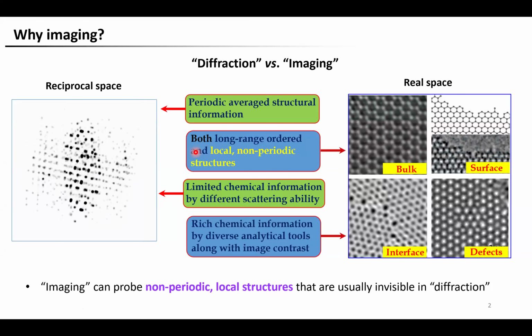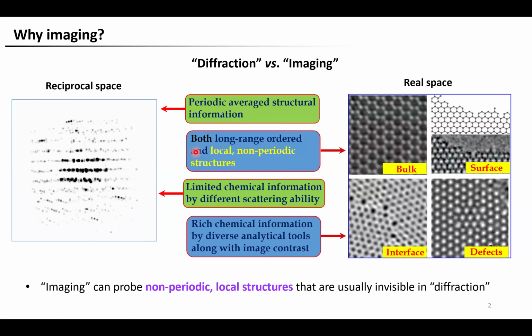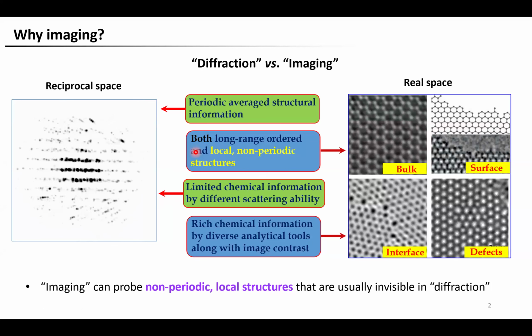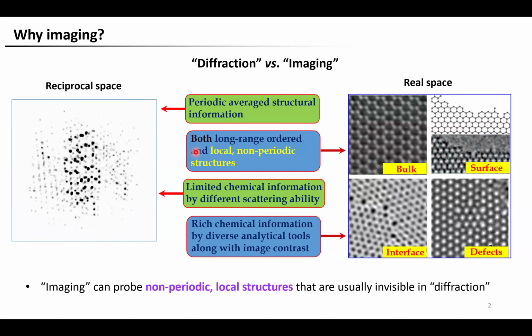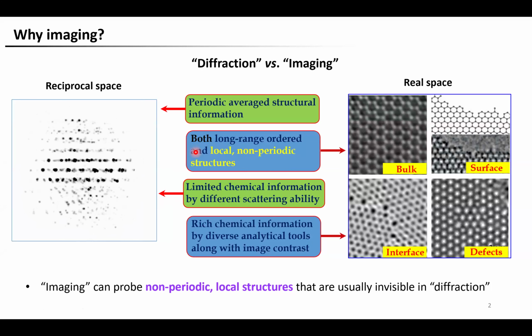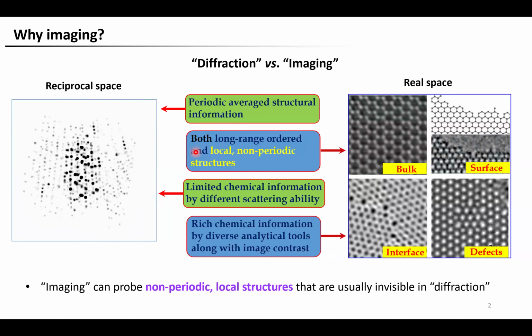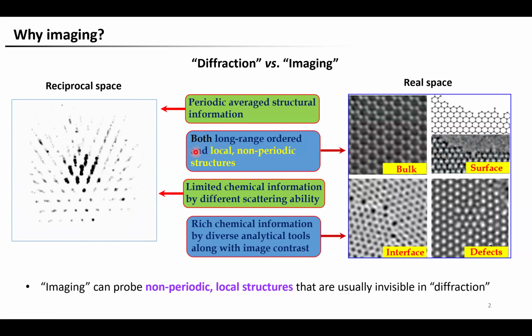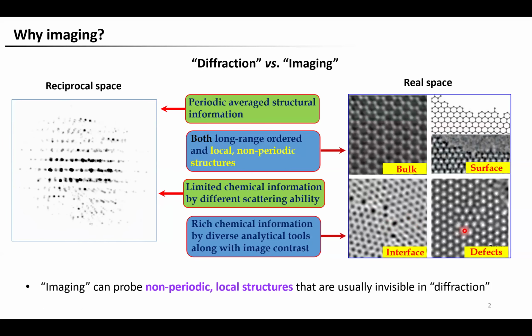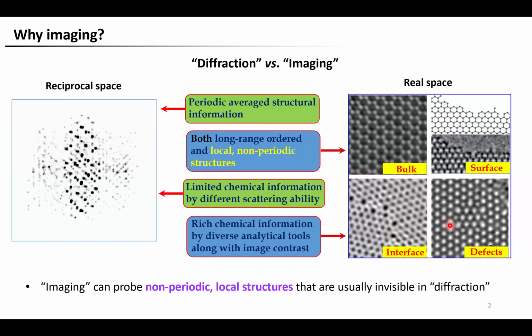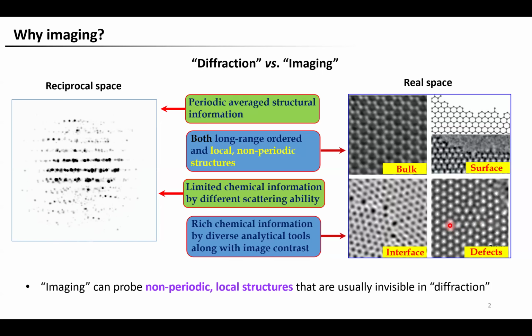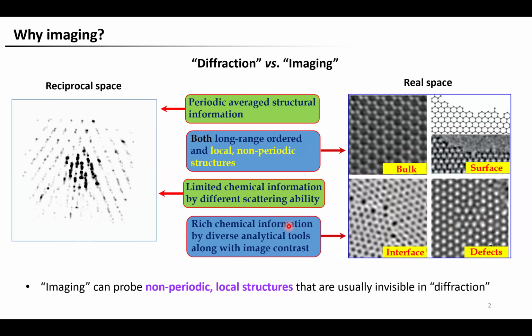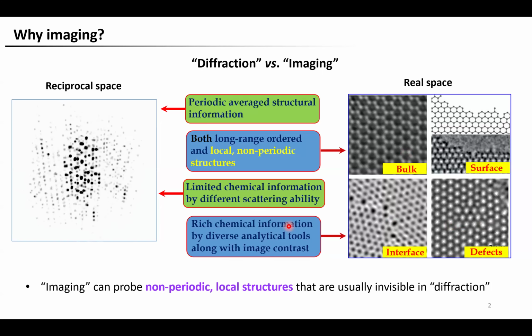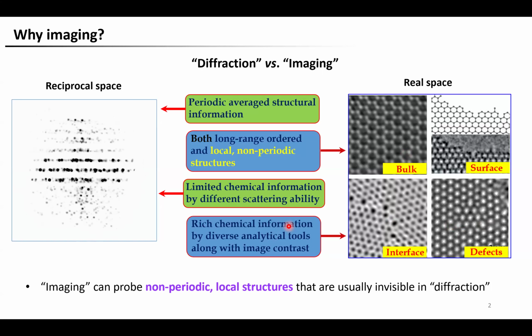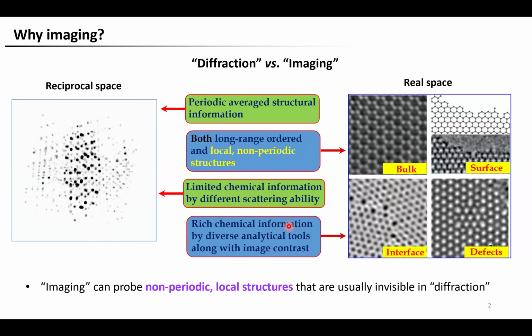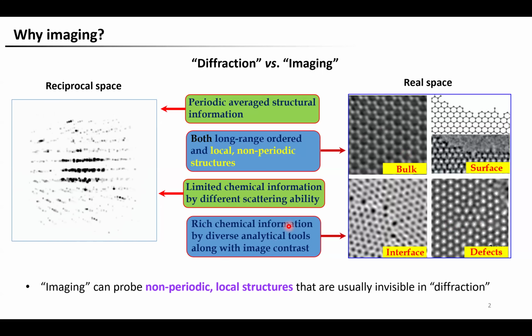Well, diffraction is a very powerful tool for determining the bulk structure of crystalline materials, as Jose just very nicely demonstrated. Well, we still need imaging to observe local structures, such as the surface of crystals, or the interface between crystals, or defects within crystals, because these local structures are not periodic, so they are not visible in diffraction. Well, with high-resolution imaging capability, for example, transmission electron microscopy, TEM, then we can directly visualize this local structure in real space.